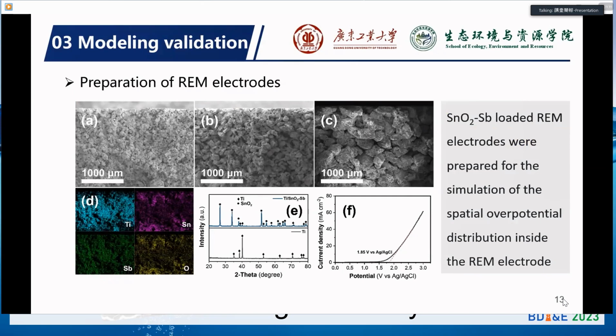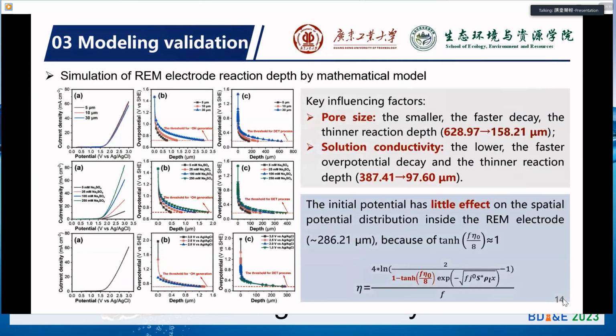So we have prepared a few electrodes for the simulation of the spatial overpotential distribution inside the REM electrode. According to the model outputs, we found some key influencing parameters include the pore size. We found the smaller the pore size, the faster the decay, and the thinner the reaction depth.